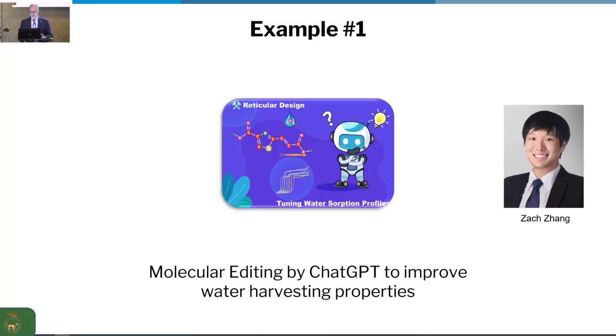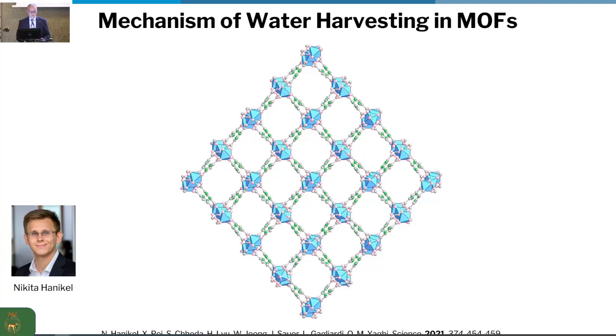Example number 1 is Zach looked at our water harvesting system and said, okay, I could use ChatGPT to molecularly edit the linkers so that we can optimize the water harvesting properties. This is a very nice water harvesting material. And we published this back in 2021 with Laura Gagliardi, but we also characterized not just the actual structure, but exactly where each water molecule goes into this structure has been characterized by single crystal X-ray diffraction. In fact, this was the occasion where I challenged Laura.